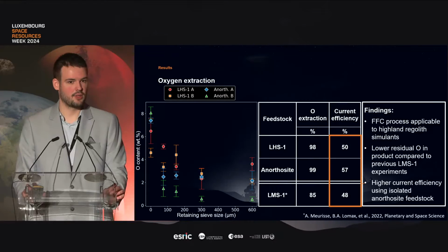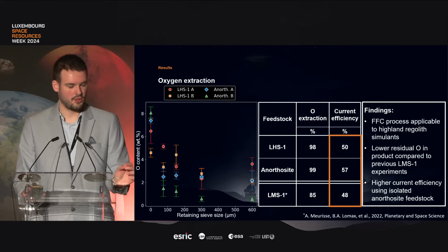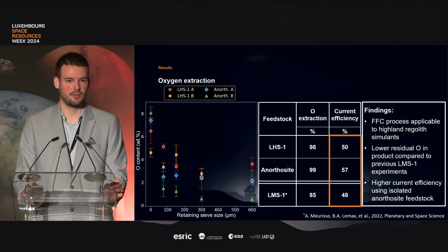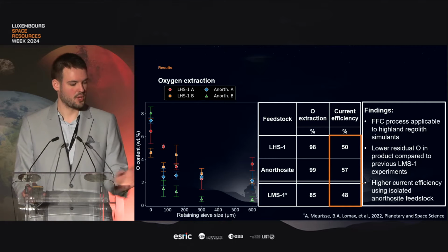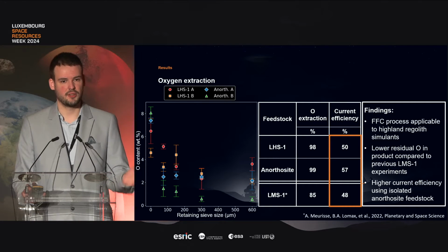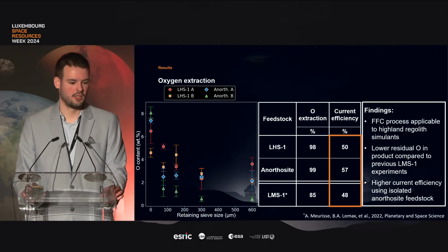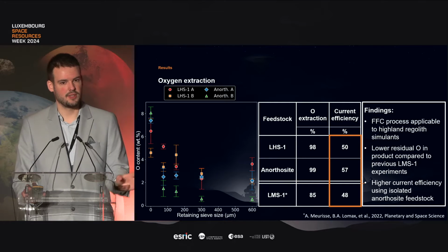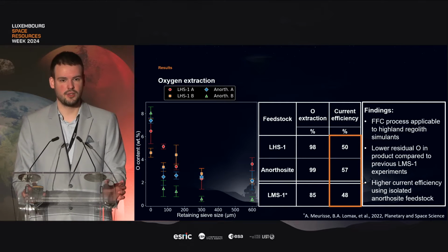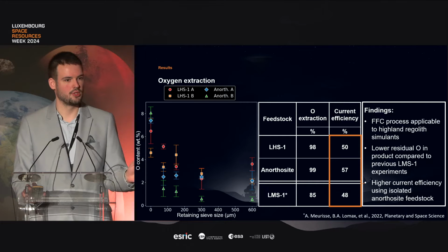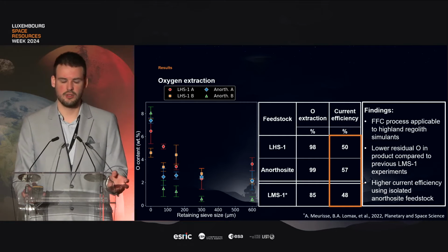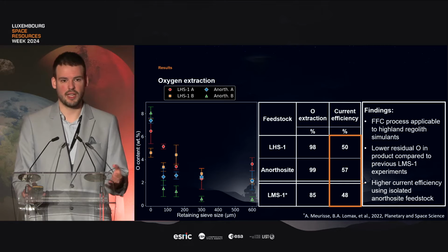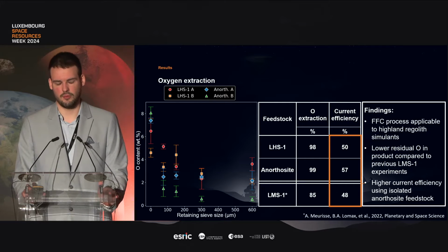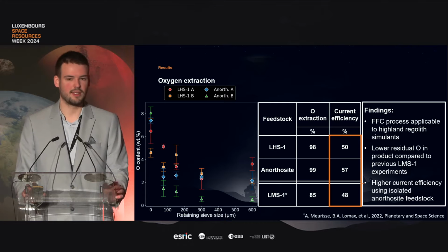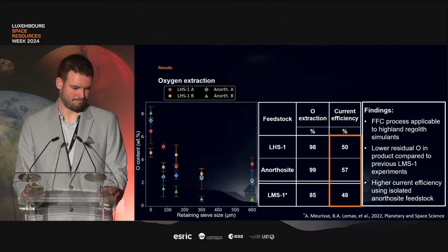Then the third point is we also see a higher current efficiency for the isolated anorthosite when compared to the LHS1 feedstock. We have about the same oxygen content, but the current we needed to obtain that was lower. Currently, based on this data, we don't really have a good explanation for it, because we can't distinguish whether this has to do with the chemical composition or maybe with the sintering behavior of the materials themselves. But I think Beth later in the session will bring some additional data points to this question.